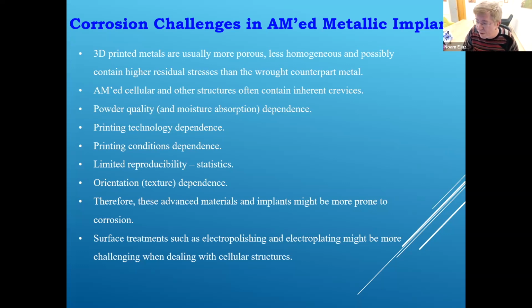It is dependent on your printing conditions and so on, the orientation or texture and so on. So there are new challenges and new things to learn that require further study with respect to the corrosion behavior of additively manufactured materials compared to the wrought alloys. And we have been doing this, for instance, we focus on hydrogen with electron beam melted powder bed fusion. This is with the Israel Atomic Energy Commission, and also with directed energy deposition, for instance, with David Zeidman.